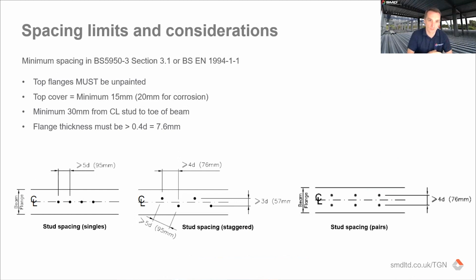So understanding that spacing limits and considerations are important. This is just a brief overview of the outline limits on stud position along a beam. It's kind of 5 diameters, so it's all related to the diameter of the stud. 19 millimeters is nearly always what we use. You can through-deck weld 22 mil diameter studs, but the design benefit of that is limited, so 19 millimeters is pretty much the go-to always, both for the TR6 up to TR60 deck, and TR80 deck is 120. But they're all 19 millimeters.